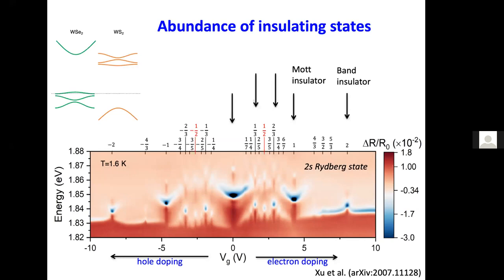This is like the response of exciton to the electron gas. They form some kind of collective excitation - people use the term polarons. You can have different collective excitations, and what we are seeing here is one of the polaron branches. It's the electron hole plus the electron sea, the collective excitation, and then you can analyze more carefully the interaction between the electron hole and the 2D electron gas in the nearby layer.